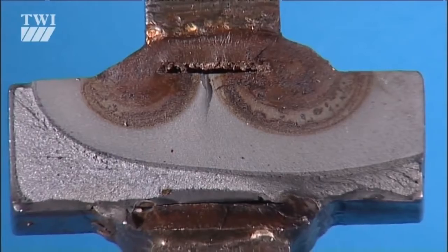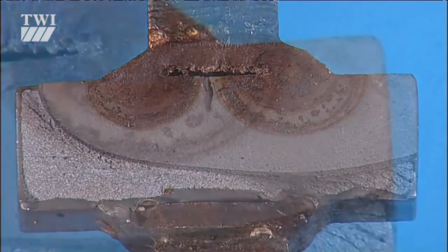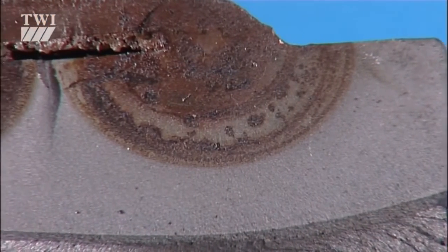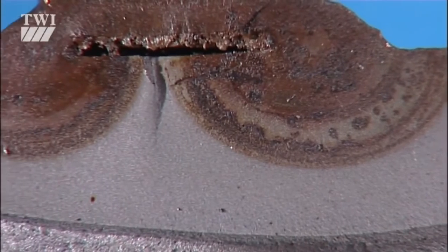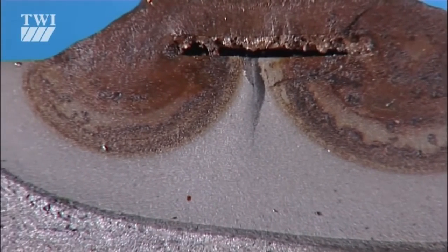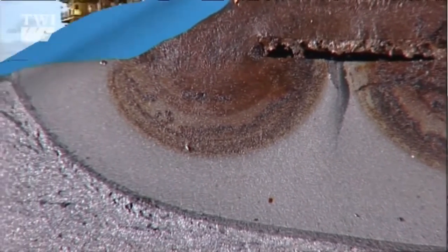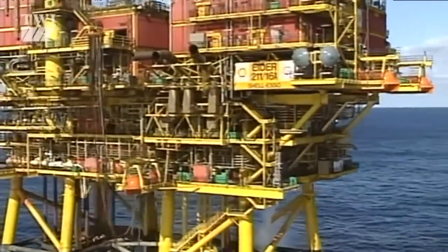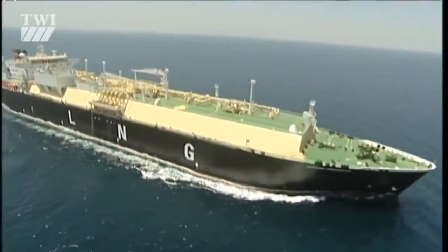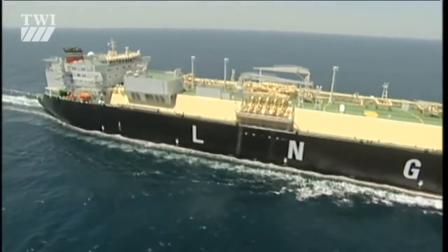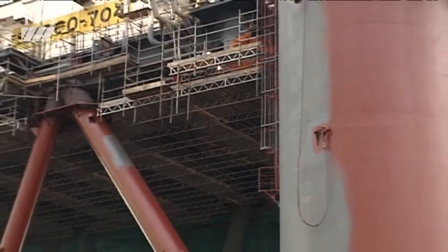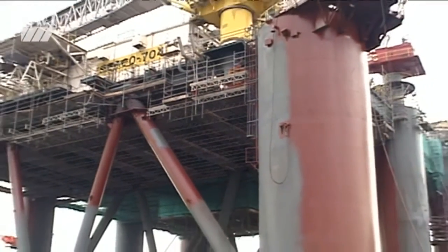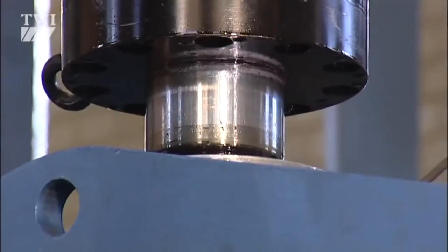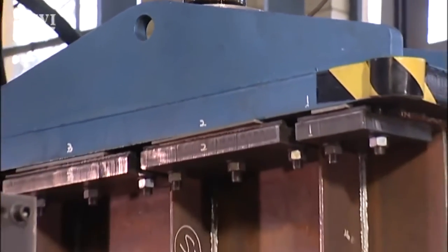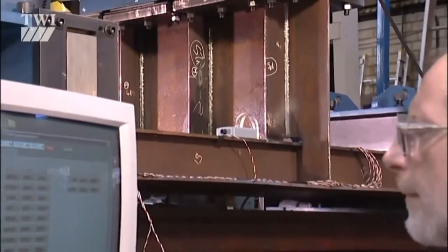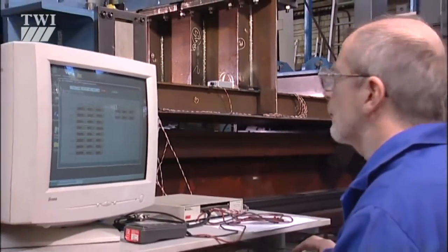Fatigue crack surfaces have a distinct look about them, a smooth appearance around the point of initiation, and well-defined steps corresponding to the last few cycles just before fracture. In practice, a degree of redundancy is often present in engineered structures. So, a redistribution of stress takes place, and the propagation of a crack may be slowed down or even halted. There's no danger of collapse, but the structure's stiffness may have deteriorated to an unacceptable level.